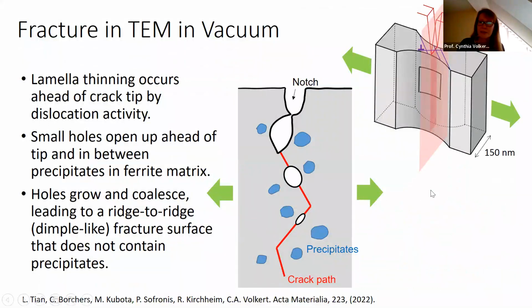So here it is summarized. You can see it thins down first by dislocation activity, and then once the region is thinned, holes open up in the lamella, and they open up between the precipitates, not next to the precipitates, and they then coalesce, and we get, as schematically shown here, a crack path that moves through the ferrite matrix.